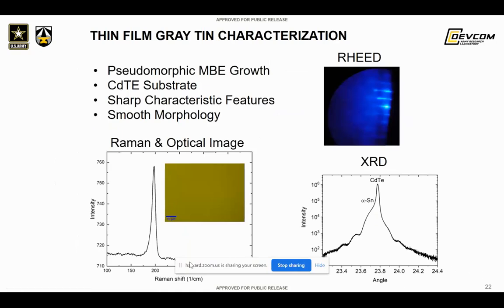In the rest of this talk, I'll talk about some experimental studies that were done on alpha tin samples that were grown on CdTe. These are transport measurements that were done. And here I show some slides of the material grown. We use various techniques to characterize the material as grown by MBE in our lab at ARL. These samples were grown at ARL actually, but on CdTe substrates.